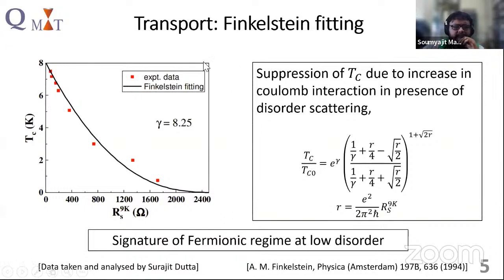Here we have plotted the transition temperature against the normal state sheet resistance, and the data we have plotted with the Finkelstein fitting, which is based on the fermionic mechanism, where the suppression of Tc was due to the increased Coulomb interaction. As you can see, the fit matches very well, at least at low disorder. So we'll see in the other measurements how this behaves in the materials.